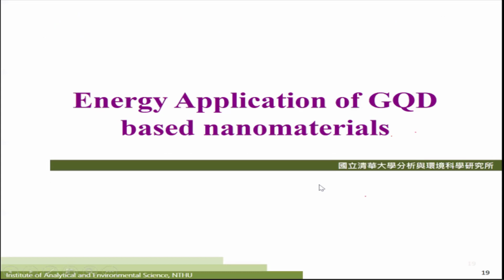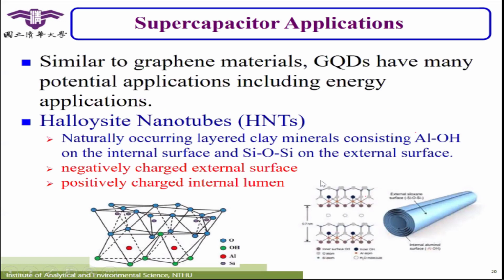For this GQD, you can do the energy application first. Since the GQD is zero dimensional, the particle size is only around 5 to 10 nanometers. It is very hard to see and to separate. So most of the time, we will use the zero-dimensional graphene quantum dots with some support. And here we select a naturally occurring material as their support. We call this halloysite nanotube. Halloysite nanotubes are a naturally occurring layered clay mineral. We can find these materials in soil.